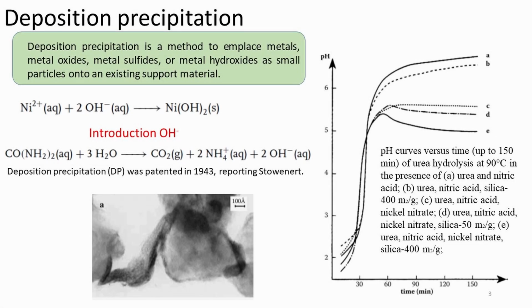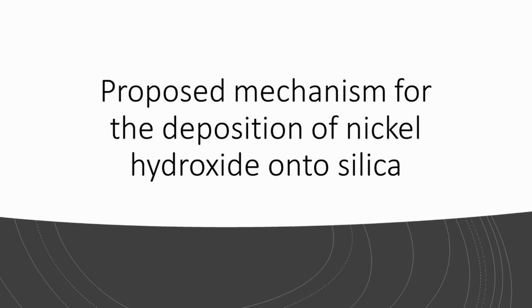and activated. As mentioned above, raising the pH is the most common way to perform deposition precipitation. It is better if the mixing and generation of the precipitant can be carried out separately. At the laboratory scale, this is possible with urea. This is a delayed base which permits mixing and basification in two separate steps. A first step, mixing at room temperature, and then basification when the mixture is heated above 60 degrees, leading to urea hydrolysis, and this leads to a gradual rise of pH. The deposition precipitation method using a base has been applied for the precipitation of various catalysts.